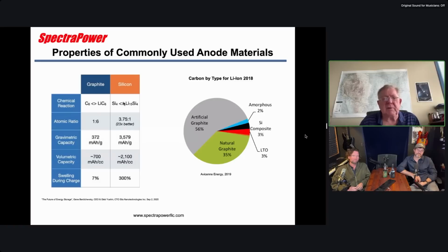Silicon is a completely different process. We refer to it as lithiation. So basically, the lithium is bonding to the silicon. Now, if you look over on the graphite, you can see you get 1 lithium for every 6 carbon atoms. If you look over on the silicon, you can get up to 3.75 lithiums per every silicon atom. So huge difference. And that's what this atomic ratio is explaining here.